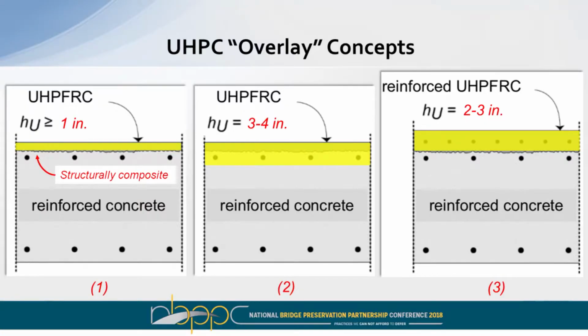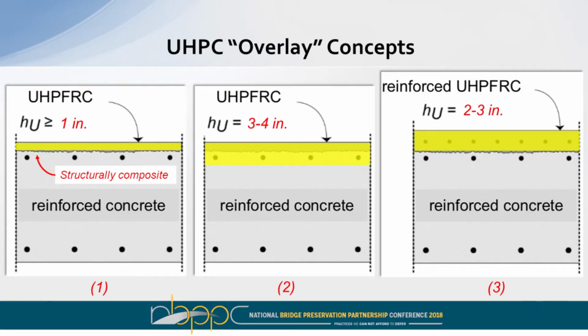But if your concrete has gone too far, your rebar has already started to corrode, you have delamination down at the rebar level, you'll likely have to remove past that point. Generally, we'd like to get about 3/4 of an inch underneath the top mat so that the material with these fibers can really get around all this rebar and surround it and encapsulate it. In the last instance, number 3, you might be looking to strengthen your section as well. So not just rebuilding back a layer, but adding some strength to it. And in that case, you can build on top and put in supplemental reinforcing steel to give you additional tension capacity where you might need it.